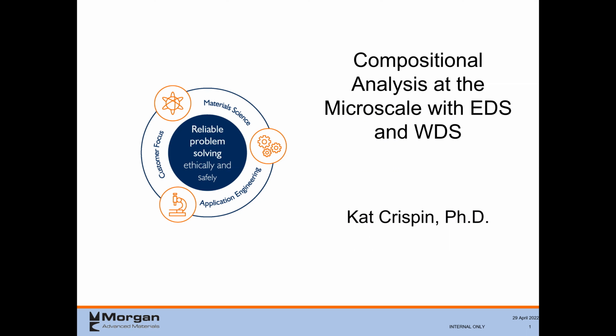So you're always going to play this game of speed versus accuracy. EDS mapping is pretty good because it's quick and you get really good qualitative information very, very quickly. But WDS takes about, I don't know, 6 or 8 times longer to do. A typical map, just what I call a quick map in WDS, takes about an hour. It's about the fastest you can do a map. And you get really nice maps, obviously, from WDS, but you're going to be playing the time game about how much time you're spending on the instrument.